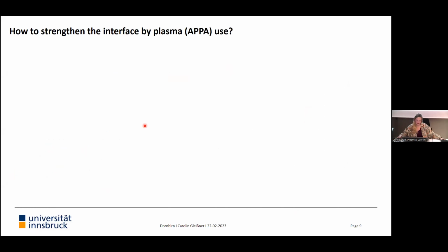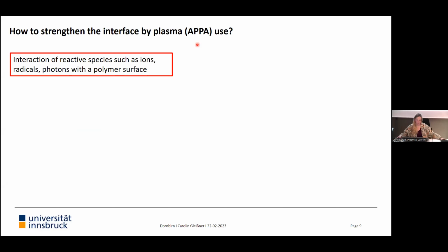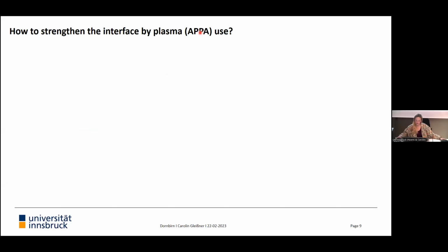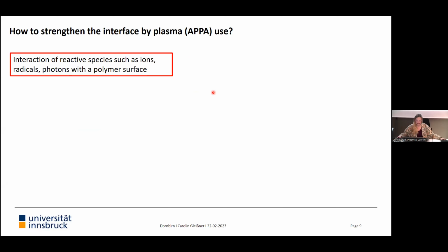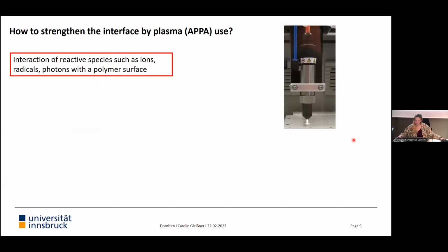So the second technique that I want to present today is the plasma treatment. We are using atmospheric pressure plasma with air, short APPA. And in the plasma, you have reactive species such as ions, radicals, photons, and these are highly reactive, so that they can react with the polymer surface. Here is a plasma pen that we are also using at the Institute. Here you can see the plasma. Plasma gases that can be used are, for instance, air, oxygen, nitrogen, argon, helium, ammonia, but what we were using is air.